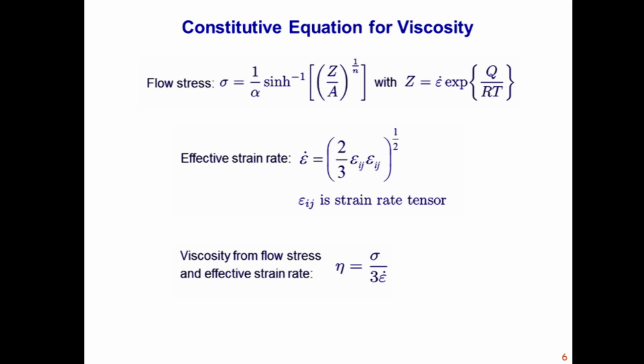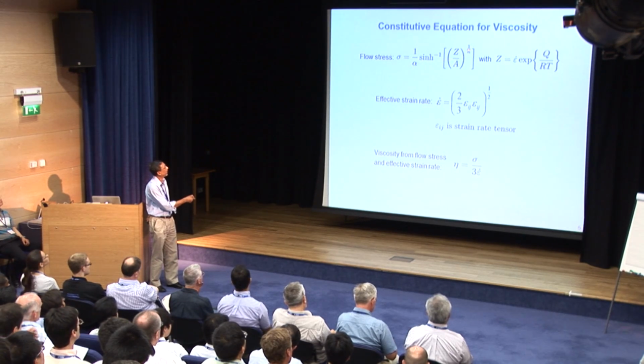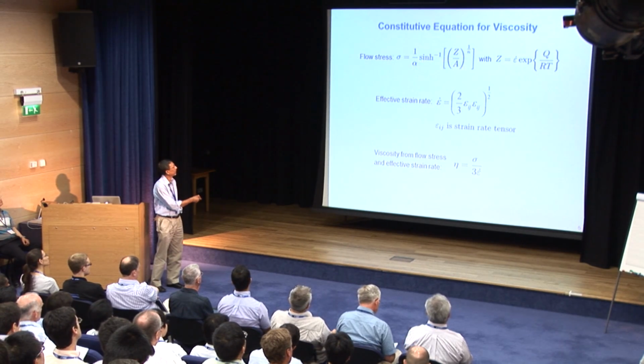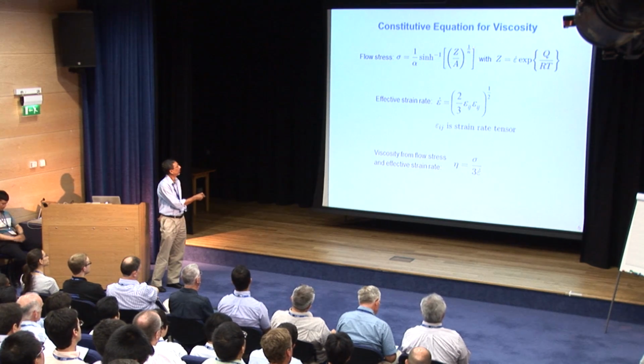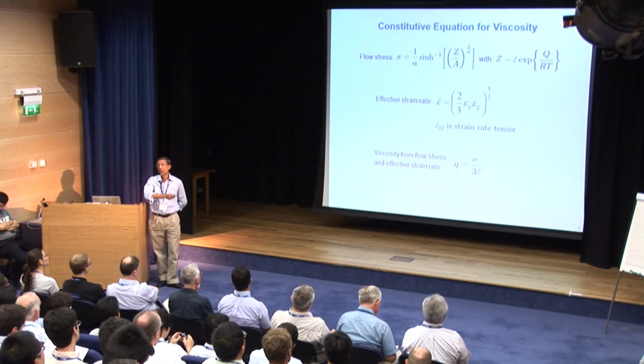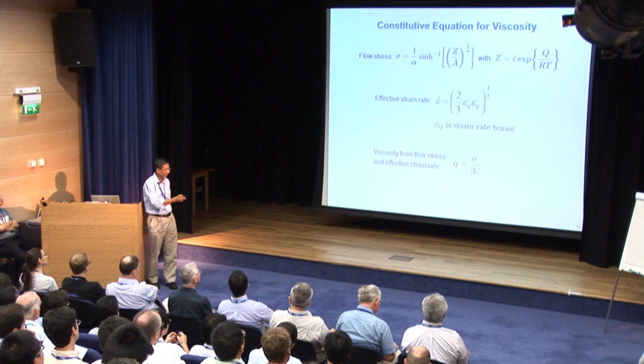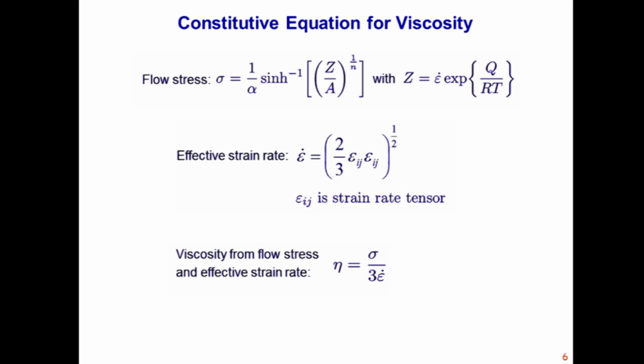And we get that model for viscosity because we are calculating 3 components of velocity. We can calculate from the velocity strain rate, and we can get a temperature compensated strain rate from the temperature, from the enthalpy equation. And these 3 parameters are material constants for Zener-Hollomon parameters, we call them, from hot working literature. So once we get these, we can then calculate the viscosity, so we can solve the Navier-Stokes equation, and we get the entire values.